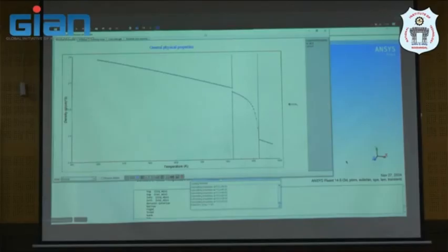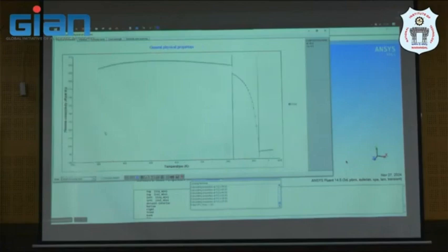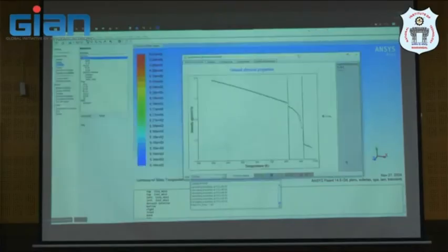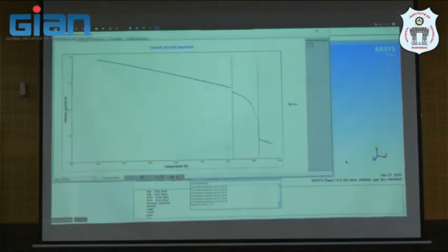Yes, and the software can provide the density. But that is assumption made for liquid viscosity and thermal conductivity. So these are all thermophysical properties that are temperature dependent, right? Yes, sure. But if the temperature goes over, let's say in this graph, over 1000 Kelvin, you will need to extrapolate or approximate it, right? That is also another point for the thermophysical properties.